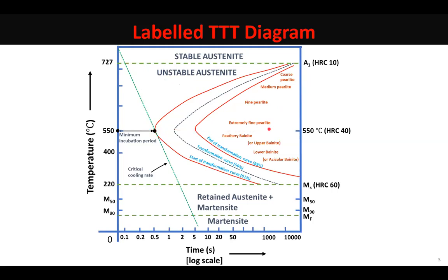Students, mind that when you initially had the steel at room temperature, you heated that steel to some high temperature so that you could have 100% austenitic structure in it. Then you held the steel at that temperature so that the austenite which has formed becomes completely chemically homogeneous, and then you start cooling the steel.